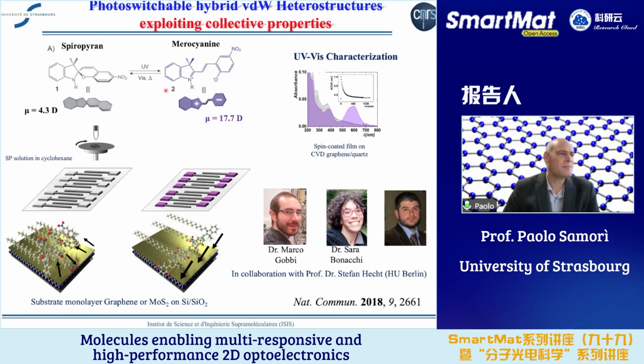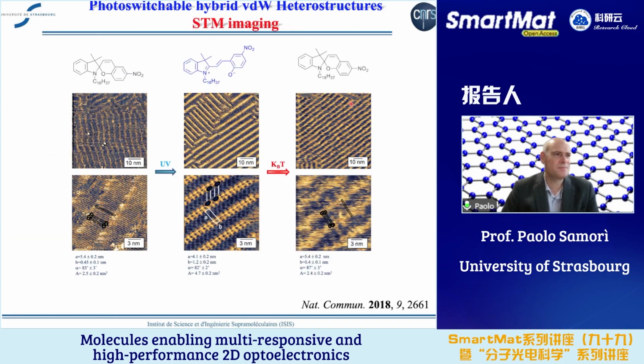The presence of these long alkyl chains forces the molecule to assemble into a lamellar structure, so to create this kind of superlattice. Now, this kind of superlattice on CVD graphene displays a photoswitch induced by the isomerization of the spiropyran that we could see when we put CVD graphene on quartz and spin coat the film of the photoswitch on the top. And this has been studied by UV spectroscopy.